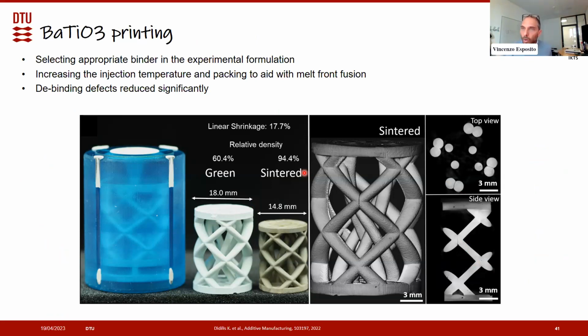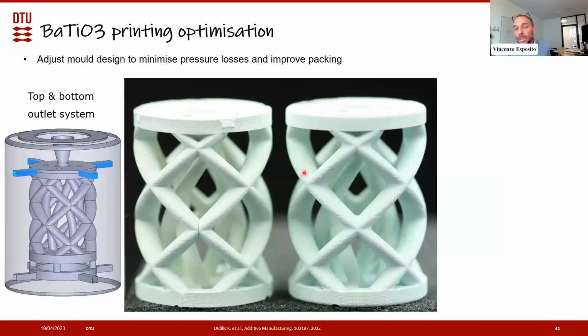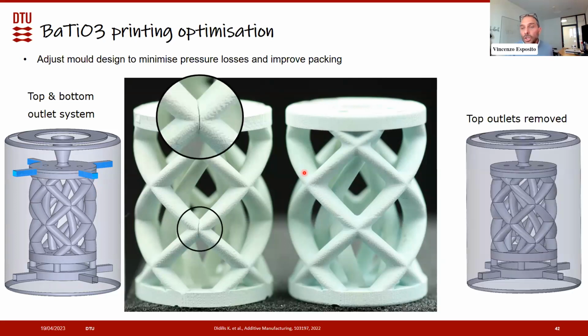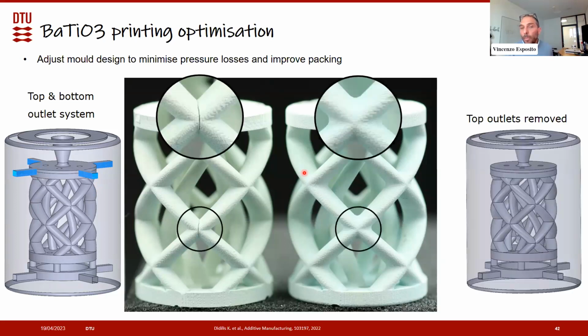And again, the flow in the mold can be controlled, and we don't have the layer-to-layer deposition or even the drop-to-drop deposition we usually have with other printing technologies. So I give you, for example, this barium titanate printing, where we show that just changing a few details in our mold can prevent the formation of cracks and other defects that are generated during the sintering, for example, where the stress can get so high and break the